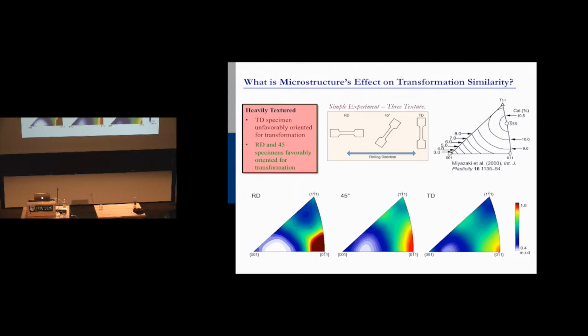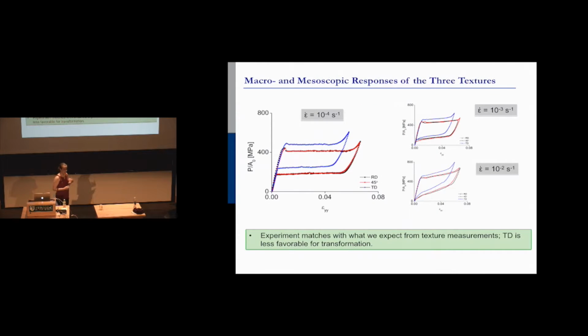Down here, things don't go so well. So the TD in there, the TD is not great. The 45 and the RD are actually pretty good for transformation. Okay, and that's what we saw when we tested these. And that's actually fairly well known, but we wanted to make sure that our material was doing what it should.